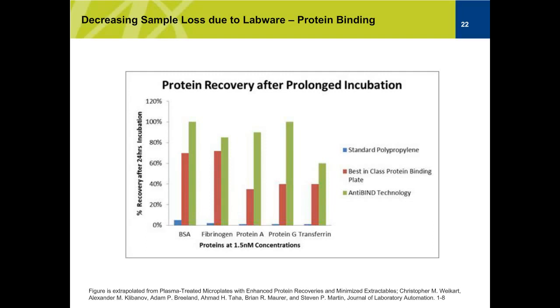And the graph in front of you is where we took five different fluorescently tagged proteins. We measured the fluorescent intensity at a concentration of 1.5 nanomolar at time 0, and then we let it incubate for 24 hours. So that's really a long incubation time. After that, we remeasured the fluorescent intensity and took the ratio between fluorescent intensity at time 0 and at time t, which is 24 hours. And then we calculated the percent recovery based on that.